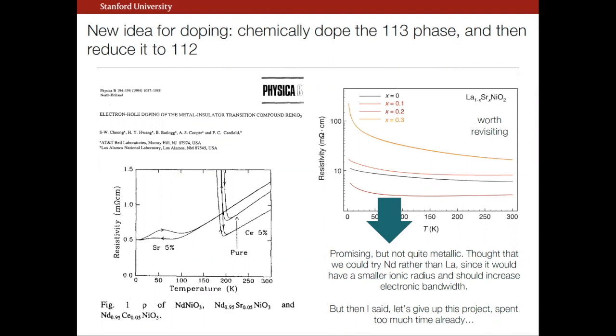And it accidentally happened that years ago, as a summer intern, at one point, I played a little bit with doping, ironically, the exact same perovskite nickelate. Right? So this is part of the way towards the superconducting compound after reduction. This is quite an interesting system. Of course, many of you know, it's a paramagnetic metal and a strongly first order phase transition to the kind of canonical charge, spin, orbital ordered configuration that we all like.